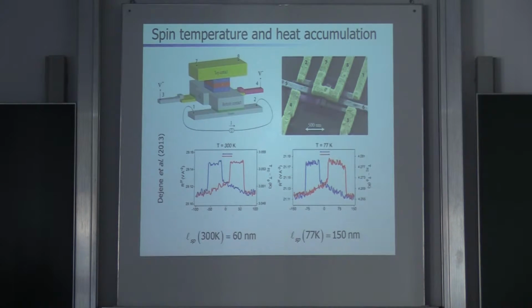Now, if you make the normal metal layer thicker and thicker, the signal becomes smaller, and from that you can derive a spin relaxation length for the heat, which is pretty long. It's 60 nanometers in copper at room temperature, and even longer at lower temperatures. Actually, this is a very funny result, because theoretically there's not a real reason why a spin temperature should exist. We know that electron-phonon scattering should thermalize the upspin electrons exactly the same way as the downspin electrons. And for electron-electron scattering, the difference is not so large.